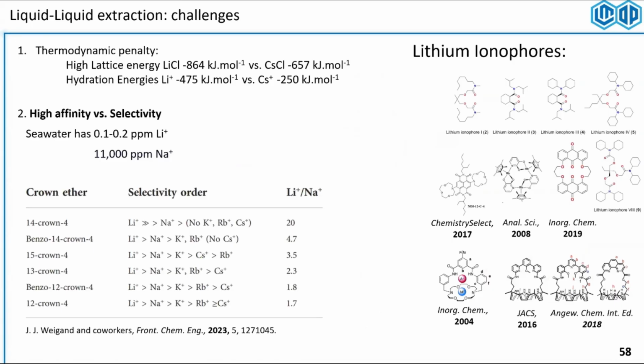There's a big challenge, though. There's a big penalty we have to pay to extract lithium out of its crystal form. They have very high lattice energies in their salts, and especially they have very high hydration shell energy around it. Lithium has this tiny space with one positive charge, so there's a big hydration shell around it. Any macrocycle that wants to grab this lithium to extract it selectively has to break through this hydration shell or break through this crystal lattice energy.